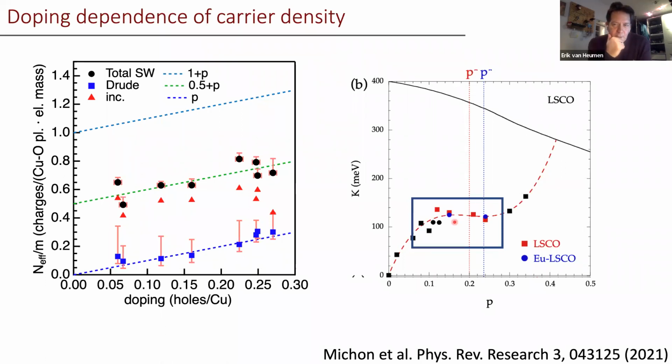And so the idea is that either magnetic fields introduce something in addition that we don't understand, or the interpretation of the Hall voltage data is simply not so simple. And you may need to write it in a slightly different way, and maybe something else is changing. Maybe not the carrier density, but for example, the transversal scattering rate, which does not necessarily have to be the same as the longitudinal one. And so that's what my data, at least what I hope to have contributed, is to that discussion in particular.